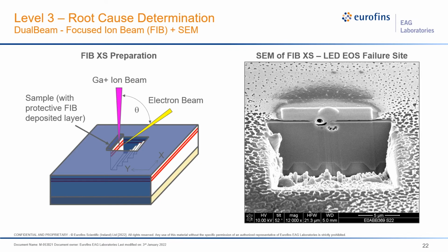In the case of dual beam, we're combining a gallium focused ion beam with an electron beam at a given angle to the two. We can use the electron beam to deposit material at first to protect the surface, then the ion beam to add a little bit more, a capping layer. And then we can use the ion beam itself to remove material, physically sputter material out of the sample.